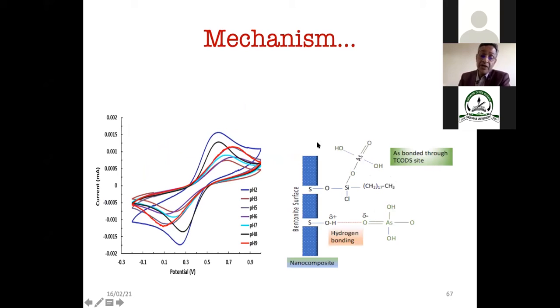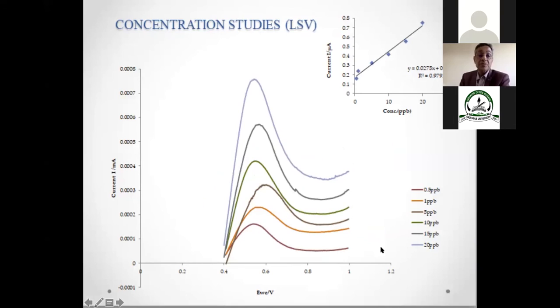But what is happening on the surface of the electrode? This is the surface of the electrode. You have introduced the silane molecule here. On this, there are two possibilities by which the arsenic is attached, and then the oxidation and reduction take place on the surface. Either by this oxygen, it is connected with silane and the arsenic is connected through this oxygen atom, or by the formation of hydrogen bonding on the surface. So either by hydrogen bonding or by this, and the mechanism was also confirmed.